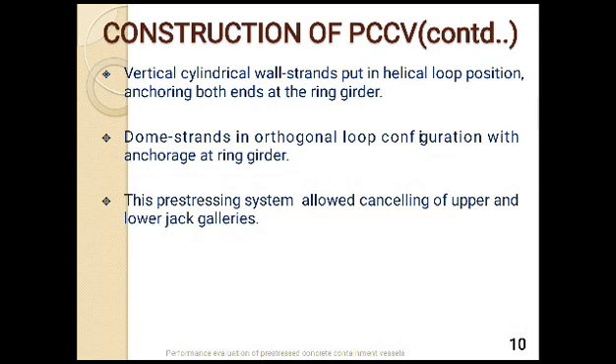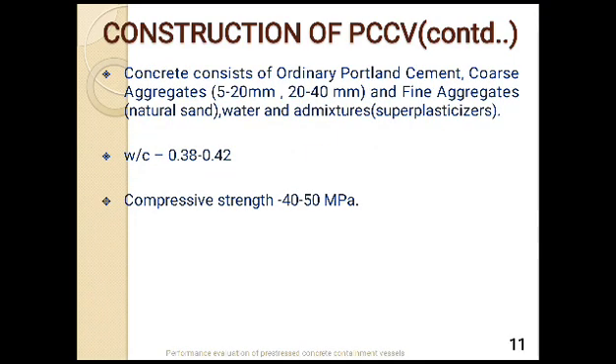Vertical cylindrical wall strands are put in helical loop position and anchored at both ends at the ring girder. Dome strands are in orthogonal loop configuration with anchor at ring girder, and this loop pre-stressing system allowed cancelling of upper and lower jack galleries. And the concrete used is ordinary Portland cement concrete, coarse aggregates and fine aggregates, water and admixtures, and the water cement ratio varies from 0.38 to 0.42, and the compressive strength of concrete varies from 40 to 50 megapascal.